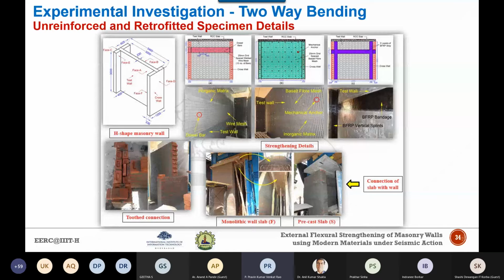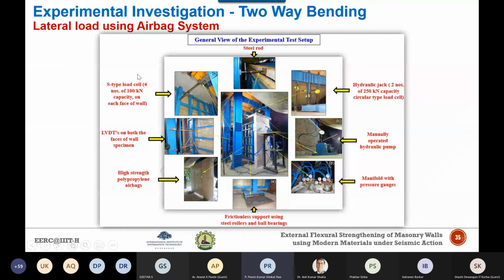For that we developed a unique test setup, where the loading has been applied using airbags. Here you can see a reaction frame consisting of 4 columns which are connected by steel beams in the loading direction, and there is a steel beam in the transverse direction. So there are 4 reaction frames, 2 steel beams in the loading direction, and 2 steel beams in the transverse direction.